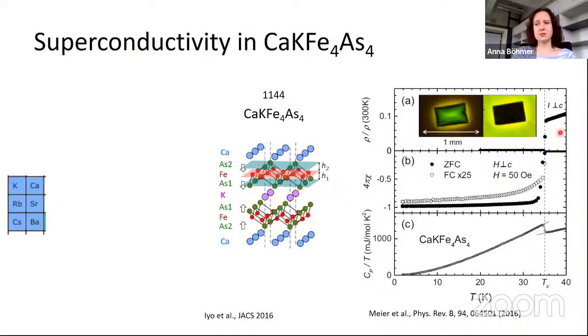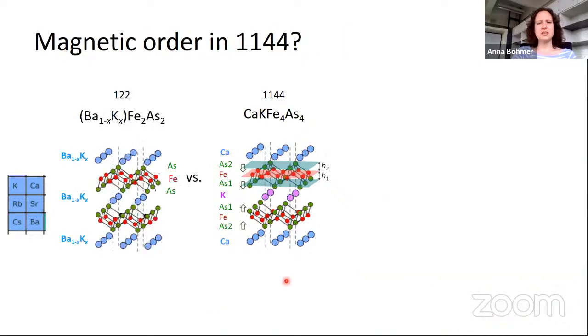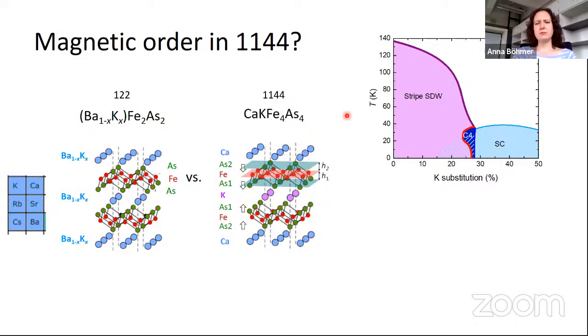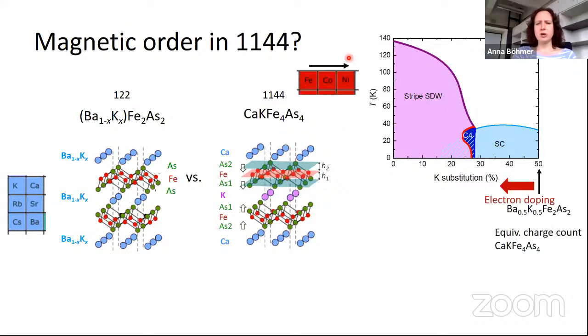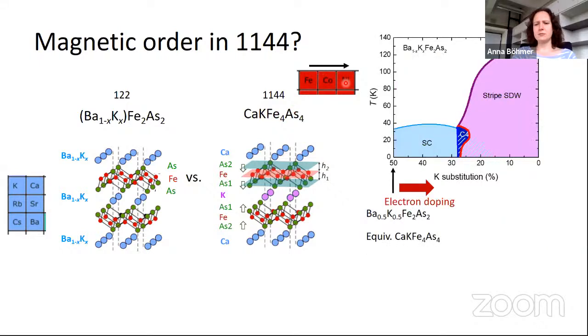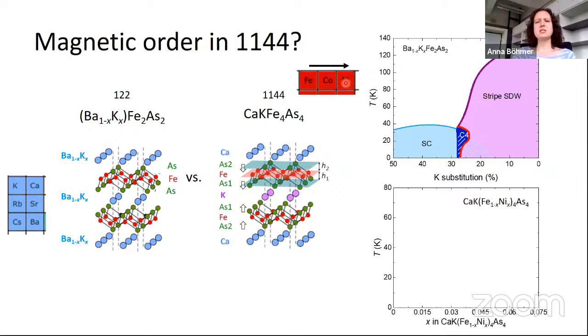You can just measure resistance again. So here's the resistance curve. Here's the diamagnetism. Here's the specific heat jump that I mentioned. It's a nice superconductor. The question was, can we get it magnetic? Can we get this compound to be magnetic by the same procedure we've used before, chemical substitution? And it turns out, if we think about it, a promising way would be to substitute the iron with cobalt or nickel. There's a reason for that, but let's just see what it gives.